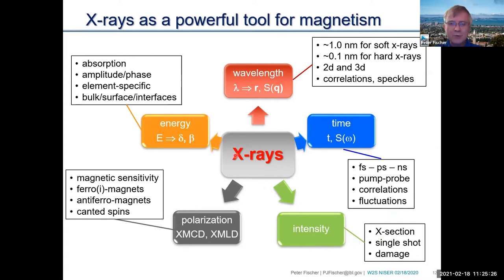Now, what is really important for studying magnetic materials with X-rays is their polarization. With polarization, it's similar to a Kerr effect, but now in the X-ray regime, just at different wavelengths. We have magnetic sensitivity, and we have what's called the magnetic circular dichroism effect, which is related to the circular polarization of the X-rays, or a linear dichroism effect. With those two effects, we can study ferro-, ferri-, as well as antiferromagnets.